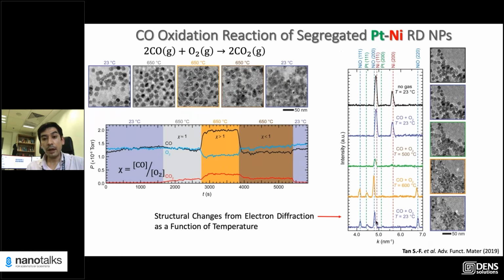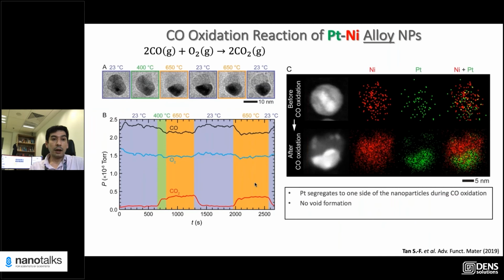And in diffraction, you can vividly see how the spacing and the thermal expansion change. You can see a shift in the peak, which tells you that as you heat up the nanoparticle, thermal expansion is going on. I'm not going to go into too much detail, but you can also do the comparison with a platinum-nickel alloy. It's not a segregated particle, but an alloy. Again, when you start the catalytic reaction, what we find quite uniquely is that it segregates out. The platinum and nickel parts of this nanoparticle segregate out nicely, and it shows the same activity. We did control experiments where we just ran basic platinum and basic nickel: very little activity for the platinum and almost no activity for the nickel.